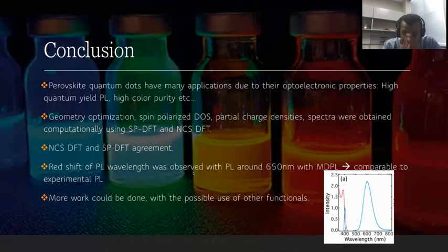So yes, in conclusion, perovskite quantum dots are very important because they have very important optoelectronic properties, and they have huge potential in many different applications, including LEDs and solar cells, because of their high quantum yield, high color purity, and high degree of tunability as well. So in this presentation, I discussed geometry optimization, spin-polarized DFT, and non-collinear spin DFT, to obtain the spin-polarized density of states, partial charge densities, and spectra for the doped and undoped models.